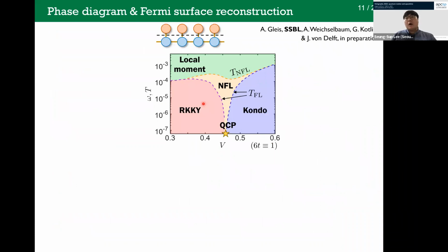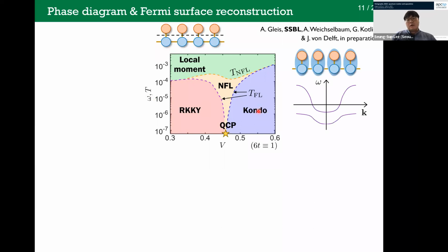Okay, good. This is our numerical result. This is the phase diagram as a function of the energy and hybridization hopping amplitude V. The y-axis is on a log scale, so it can be either frequency omega or temperature T, because these dashed lines are crossover lines that distinguish different physical regimes, say phases. In the highest temperature regime, the f electrons are effectively decoupled from the rest of the system, so they are in the local moment regime. And when V is large and temperature small, the Kondo screening wins, so the system is in the Kondo phase, where the band structure has this two-band feature.